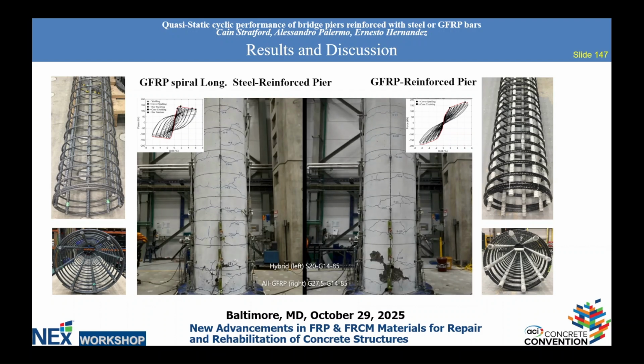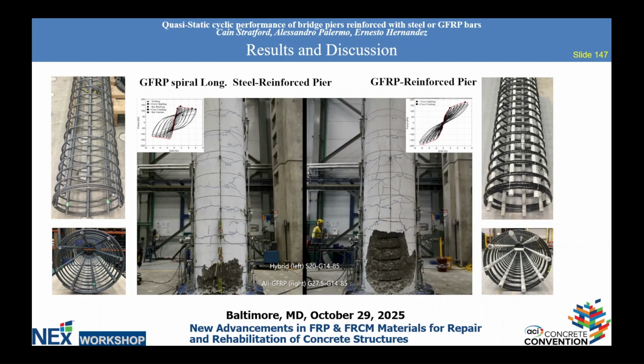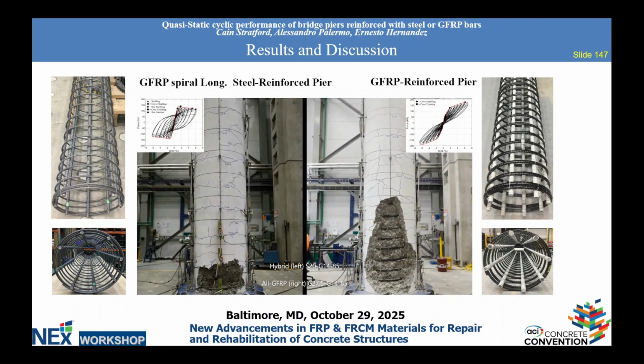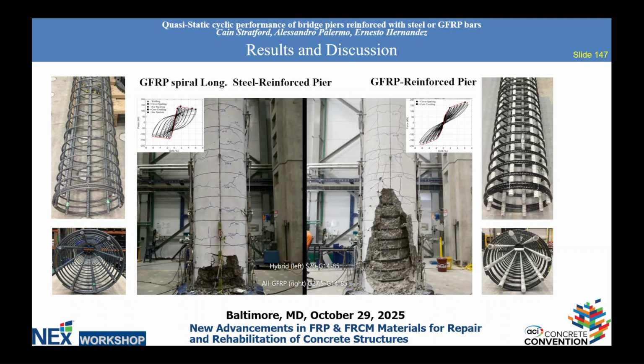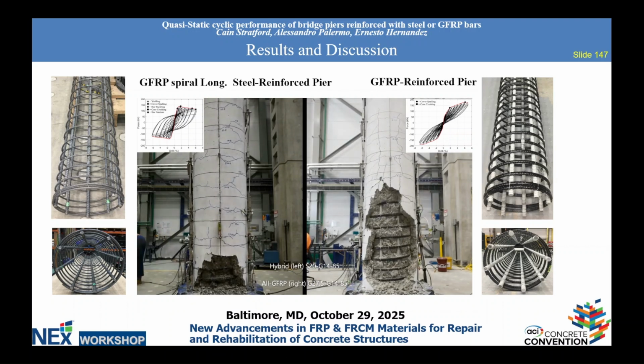have the recentering. So if you look at the test, now what happened, because they've been designed at 30% of their ultimate strength, due to the sustained load, you will see that if you keep loading, here you have a plastic hinge, which was 14 inches. The plastic hinge developing here is 3 times more, because the bar keeps picking up. Now you will say this is bad, because you have more damage. I agree with you, but it's also positive because the material is elastic. So after the earthquake, technically, we have just to patch the surrounding. So it's a sort of elastic hinge, if you wish.